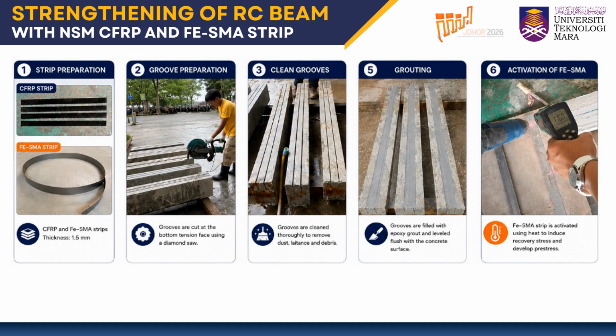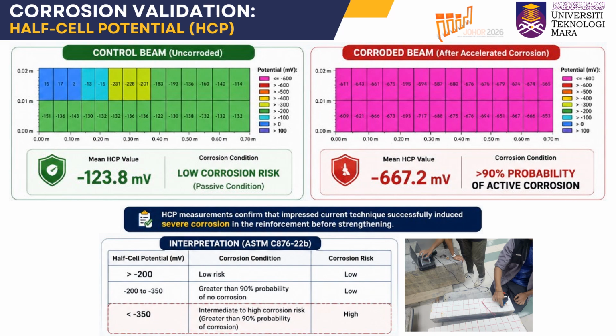The strengthening procedure began with groove cutting along the beam soffit using the near-surface mounted technique. After cleaning the groove, CFRP and Fe-SMA strips were installed and bonded with epoxy grout. Thermal activation was applied to the Fe-SMA strip to generate recovery stress.